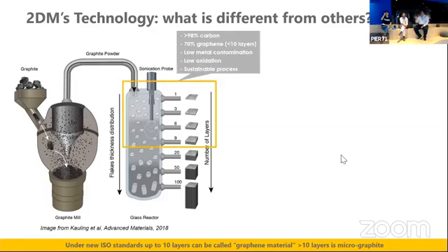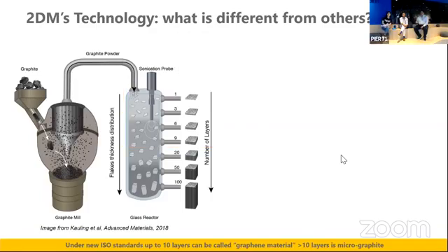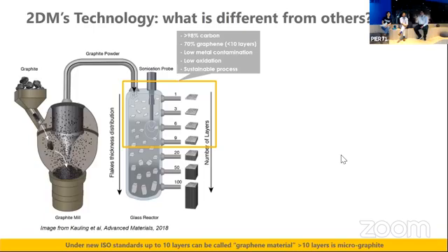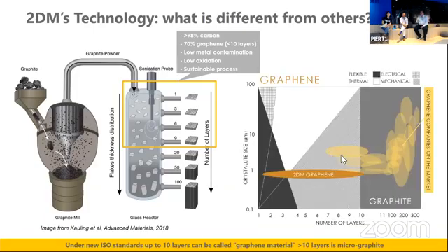Meaning that if we start with 1 kg of graphite, we end up with 700 grams of graphene. Our competitors normally can do very few percentage, 1%, 2%. This is why graphene was very expensive in the market previously.